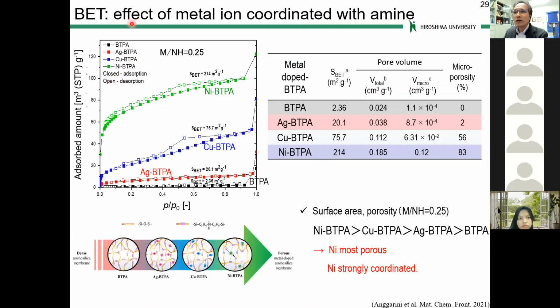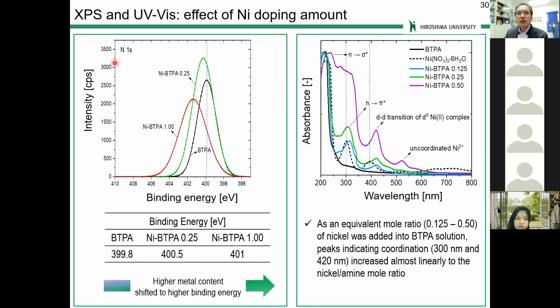Here we have the data on the effect of the metal ion. In the case of the pure BTPA, silver dope, copper dope, nickel dope, this table summarizes the surface area with doping amount and doping species. As you can see, the same mole ratio was doped. Nickel is most porous. So this suggests nickel is strongly coordinated. This coordination was confirmed by using XPS and also UV spectra.